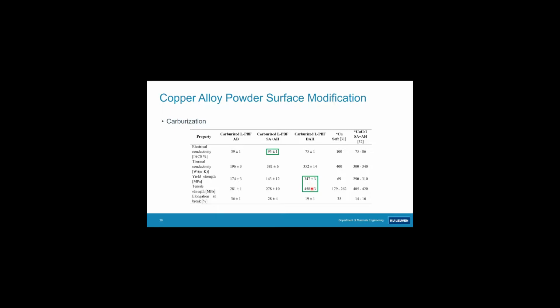So in this case, we formed a material with a very interesting combination of yield strength and tensile strength, also quite decent work hardening behavior. This is in the direct aged state combined with an electrical conductivity of about 75%, which corresponds to a thermal conductivity of about 350 watts per meter Kelvin. In the solutionized plus age-hardened state, your precipitates grow more, you have a more purified copper matrix, so your conductivity increases a lot, but you compromise on the tensile strengths. So for heat exchange applications, you basically look at the combination of thermal conductivity and strength. We would probably opt for this material.